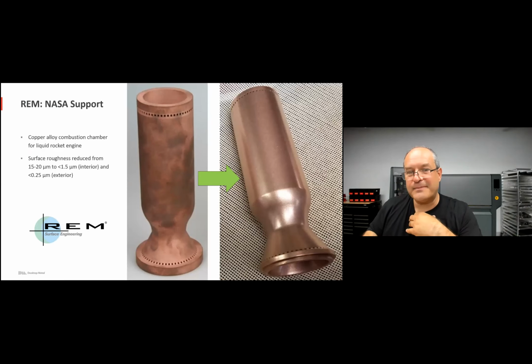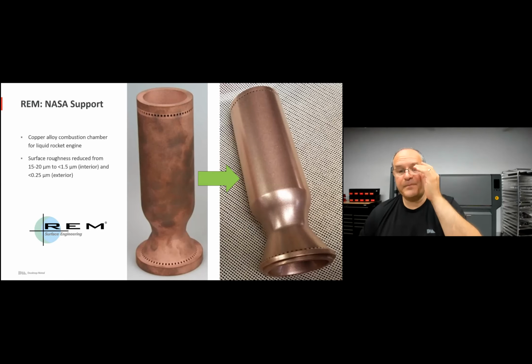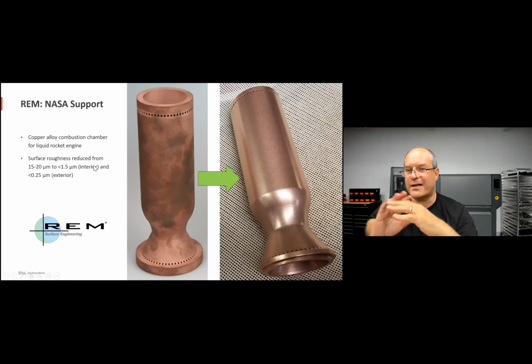As an extreme example of what the REM team has done for NASA, here's a copper alloy combustion chamber for a liquid rocket engine. It started out with a surface roughness both inside and outside of 15 to 20 microns, which is typical. With the REM surface process, they could get it down to almost 100 times smoother on the outside, less than a quarter micron, and better than 10 times smoother on the inside, less than a micron and a half surface roughness.